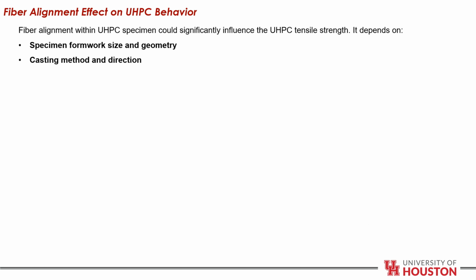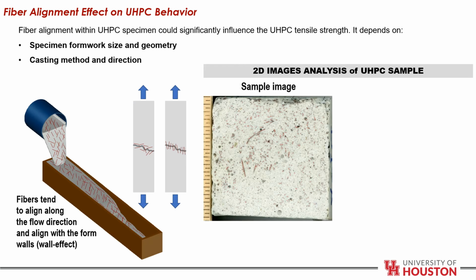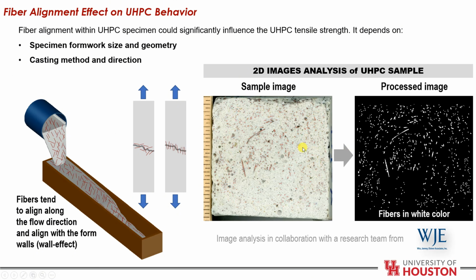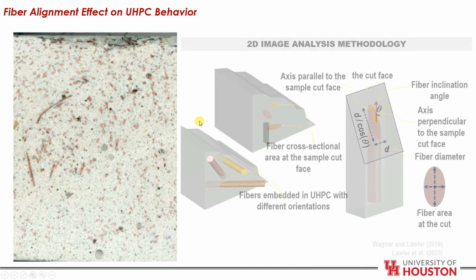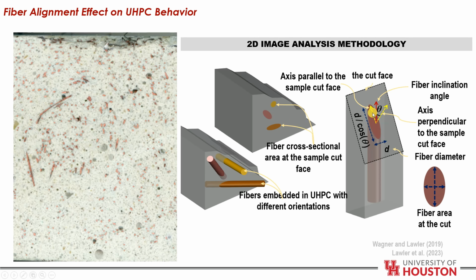The other part of this study is the fiber alignment, which is a key parameter in UHPC tensile strength, and it depends on the specimen formwork size and geometry and casting method and direction. So if fibers are aligned in a favorable direction, the tensile strength will be enhanced. Otherwise, there will be variation in the tensile strength response of UHPC. The study was conducted by extracting specimens from the panels and analyzing the images, and based on the area of each fiber through the section cut, the fiber orientation was calculated.